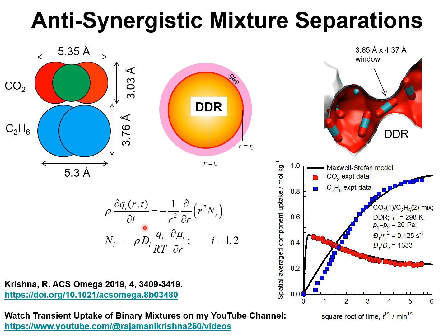This time derivative is related to the molar flux of species i, and the molar fluxes are described by the Maxwell-Stefan diffusion equations as being proportional to the gradient of the chemical potential of species i, and the proportionality constant is the Maxwell-Stefan diffusivity Di. Rho is the